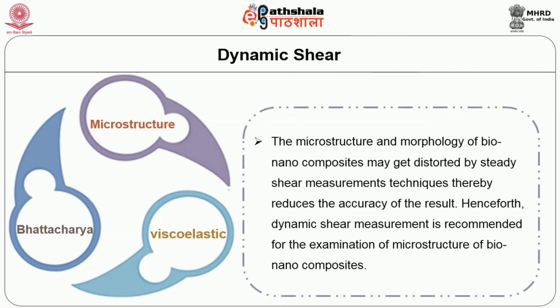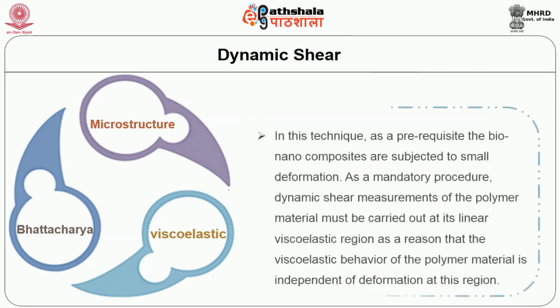The microstructure and morphology of bio-nanocomposites may get distorted by steady shear measurement technique, thereby reducing the accuracy of the result. Hence, the dynamic shear measurement is recommended for the examination of the microstructure of bio-nanocomposites. In this technique, as a prerequisite, the bio-nanocomposites are subjected to small deformation. As a mandatory procedure, dynamic shear measurements of the polymer material must be carried out at its linear viscoelastic region, for the reason that the viscoelastic behavior of the polymer material is independent of deformation in this region.